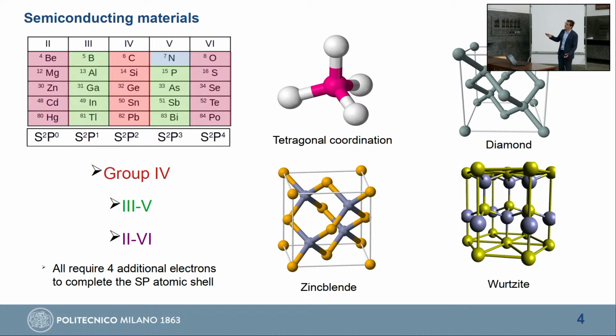So you see that now the average is still S2P2 as an orbital configuration. And so now it will be essentially similar to the diamond structure, but now we have 2 different atoms, a central one, which can be group 5, and the other 4, which are group 3. And also many 2,6 materials follow this crystallization. And we have several materials. The more relevant ones are those involving nitrogen, which is very electronegative, which form this wurtzite structure where you can still recognize this tetragonal coordination for filled shells. So basically, if you take this group 4 element or you mix 3,5 or 2,6 materials, with a very high probability, you end up with a semiconductor.